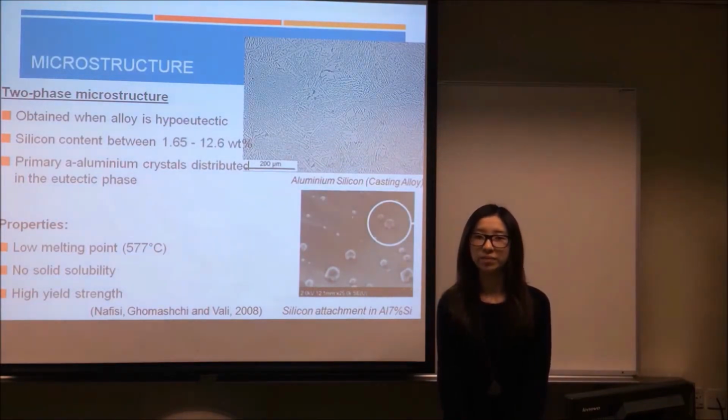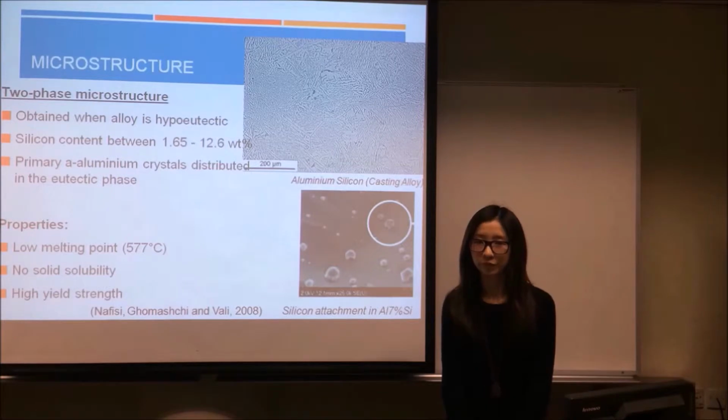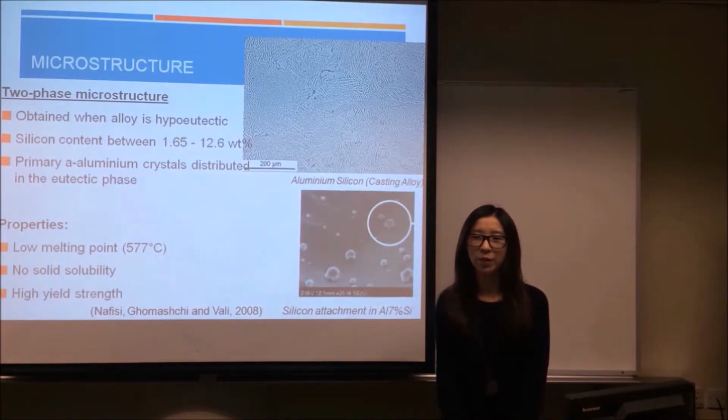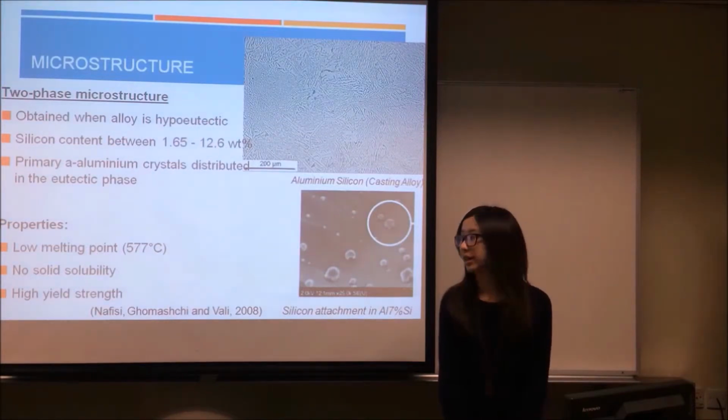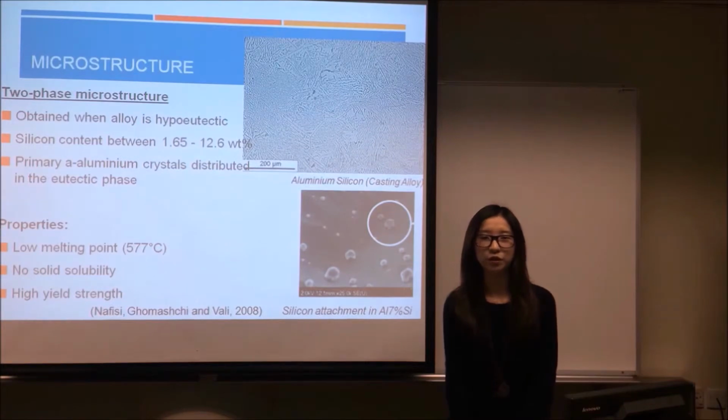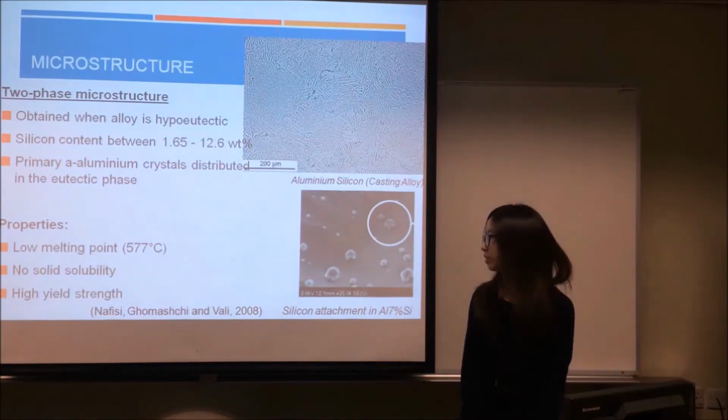Aluminium and silicon have no solid solubility below the eutectic, and the microstructure solidifies as silicon particles in an aluminium matrix. The precipitate phase acts as an obstacle to the motion of dislocations through the aluminium matrix, thus raising the yield strength inversely proportional to the interparticle spacing.